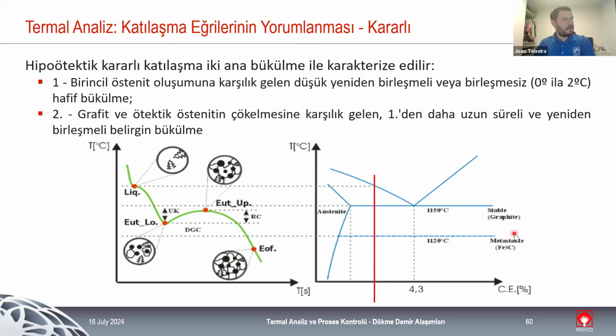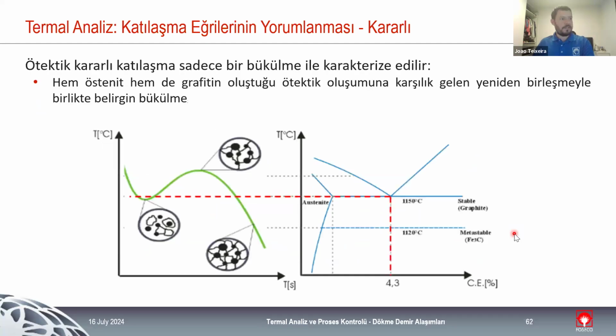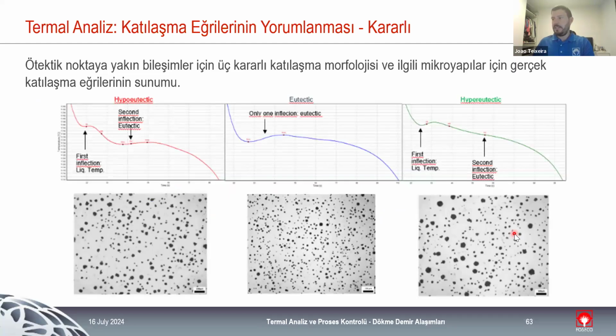And this is a more detailed explanation of what we discussed: the hypoeutectic solidification, hypereutectic, and eutectic solidification. And in here with examples with microstructure, and we can see clearly that there are some big differences in the microstructure. We are dealing with exactly the same type of cast iron in this example, nodular, but slightly different values of carbon and silicon, so slightly different values of carbon equivalent, means that we have a completely different structure in the cast. So we have different mechanical properties, we have different types of solidification that are going to affect the type, for example, of gating system that we are going to use, sleeves, etc.